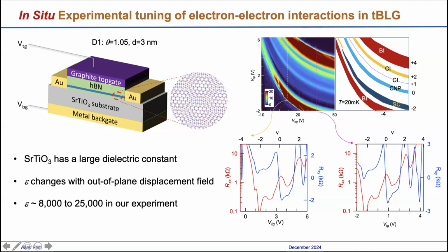If you look at this phase diagram, one feature is that it's immediately different from the case where you have hBN back gate and top gate, or silicon oxide dielectric. Here these features are curved, meaning that the ratio of capacitive coupling between the back gate and top gate is changing. It's not constant. The top gate is just hBN, and we can verify this with Hall resistance measurements. The top gate is very well behaved, just linear, which means that the dielectric constant of the STO back gate is changing. We can estimate that the dielectric constant ranges from 8,000 to 25,000 in the experiment, being larger near the top and smaller near the bottom right.